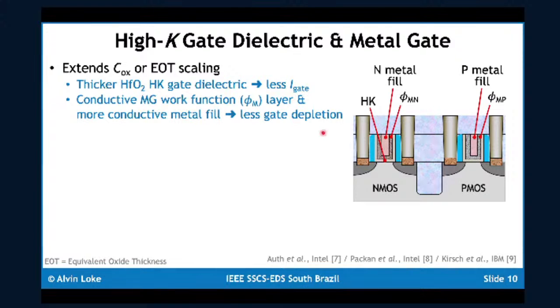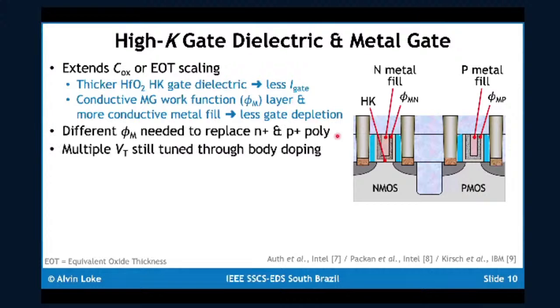Because we are replacing both N+ and P+ poly gates in a planar, non-HighK metal gate process, you need a different work function metal to achieve that for both NMOS and PMOS, since you essentially need work functions that line up with the conduction band edge and valence band edge of silicon.